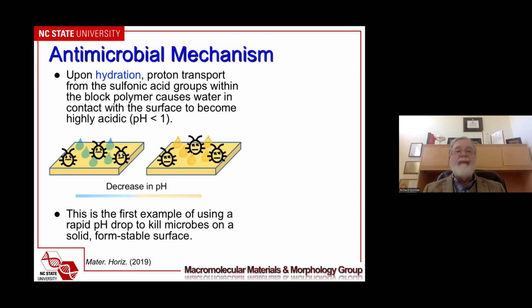So the mechanism is very simple. Upon hydration, protons from the sulfonic acid groups within the block copolymer migrate to the surface. They force the contact layer, the aqueous contact layer that resides at the surface, to decrease in pH.